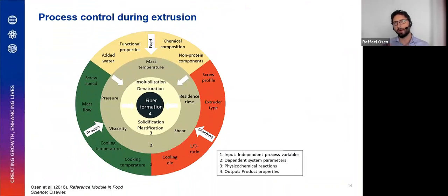Now, the one advantage of the extrusion process is that it's a one-step process that can be scaled up and that can be industrially used. On the other side, this one-step process makes it also challenging in terms of product development, because there are many influencing factors that all are intertwined. So whenever changing one process parameter, then the rest of the process parameters are changed as well. And this graph basically breaks it down into 3 categories: the feed, the raw material categories on the top, and the machine parameters such as the screw profile, the extruder type, the size, the cooling die, and then the process parameters, the screw speed, mass flow, cooling temperature, and so on.